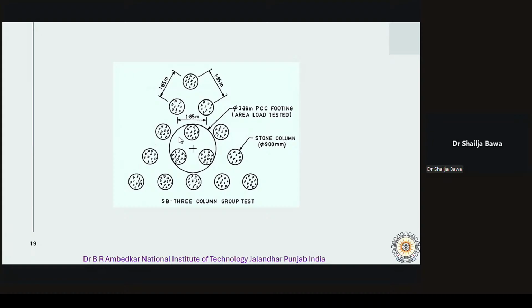So here again, the initial and final soil conditions at the trial site should be investigated by drilling at least 1 borehole, and 1 static cone test or the pressure meter test or the dynamic cone test should be done to assess the properties of the soil. After that, a granular blanket of medium to coarse sand having thickness not less than 300 mm should be laid over the test columns. Okay, first of all, the test columns are prepared, and over that we have to put a blanket of the coarse sand. The thickness should not be less than 300 mm. Okay, and over that blanket, then we have to provide the properly designed footing.